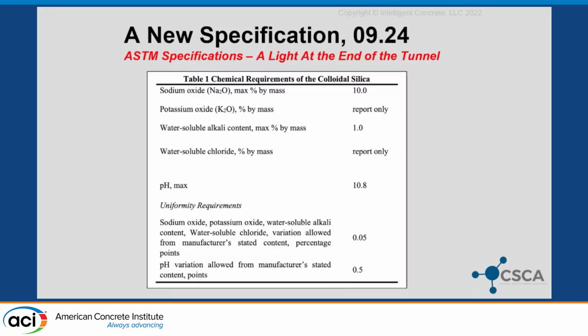We're about one more ballot away, maybe a second ballot away, from getting this ASTM done, and this is one of the tables. This is for our chemical requirements of the colloidal silica, and it goes through what we should expect out of a standard colloidal silica and ways that you can easily measure it. With something like this, you should be no more than 28 days for verifying what you have. The ultimate idea was to give the end users and the manufacturers a way to verify that what they purchased, the colloidal silica, is in fact colloidal silica and is uniform to what they ordered off the website.